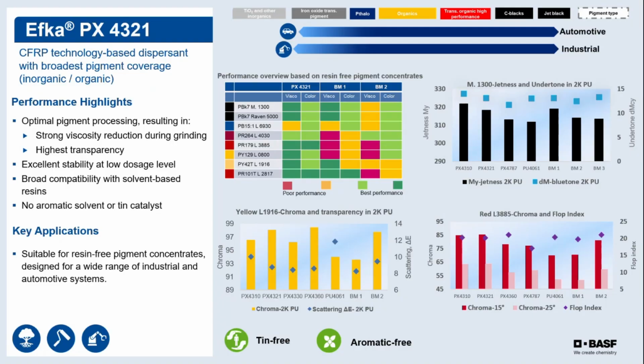And then, as I mentioned, it also works excellent for transparent iron oxides. In the lower left, we have yellow L1916. So this is a yellow transparent iron oxide. Here we have 2 aspects that we show, chroma and transparency. And you can see the chroma, which is represented by the yellow histogram. You want that to be as high as possible. And 4321 has one of the highest histograms. And then in terms of transparency, we characterize this by scattering. And you want that blue diamond to be as low as possible. So you can see the 4321 has an excellent balance of those 2 properties.